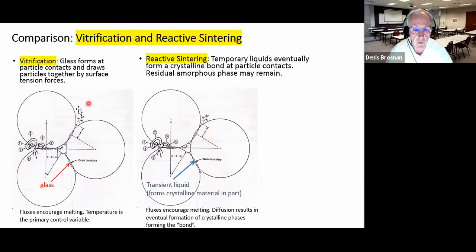So that's the difference. In the case of vitrification, we form a liquid, and in fact, we can form some minerals, particularly in clay ceramics, a mineral called mullite we'll talk about later in the course. But in reactive sintering, the liquid primarily disappears or becomes not the major factor in the bonding between these adjacent particles. So those are 2 types of sintering processes.